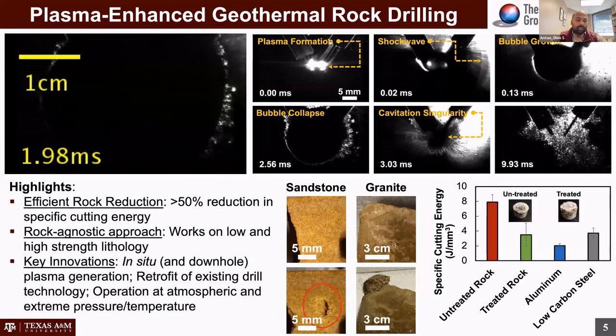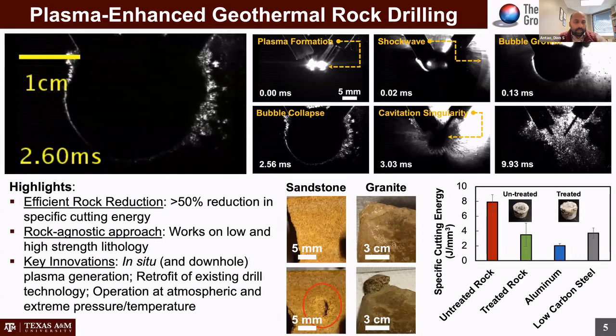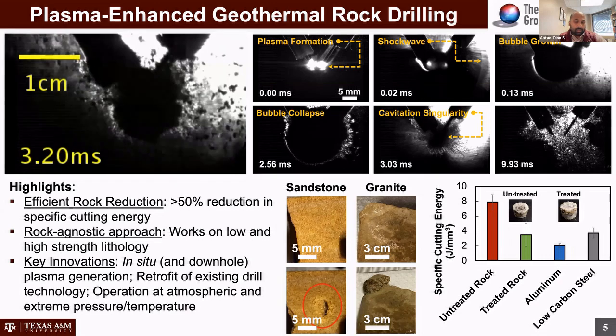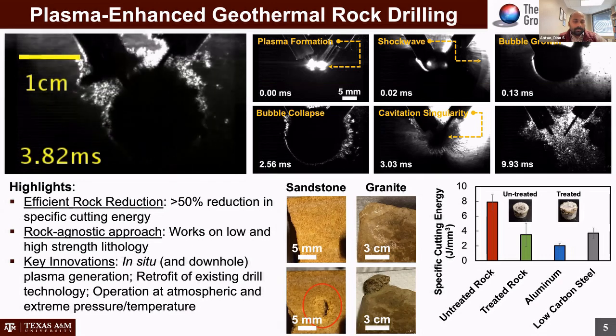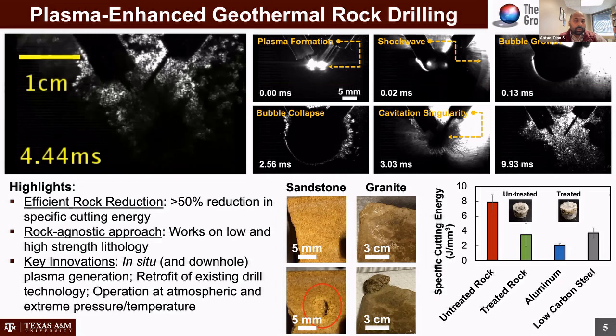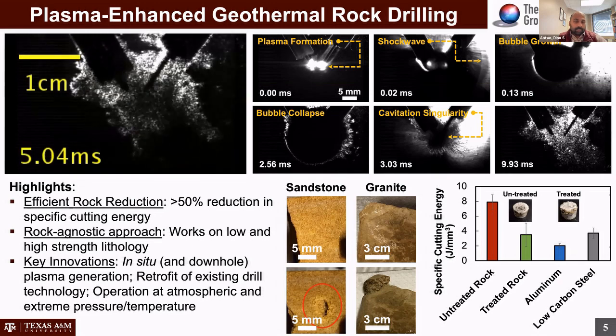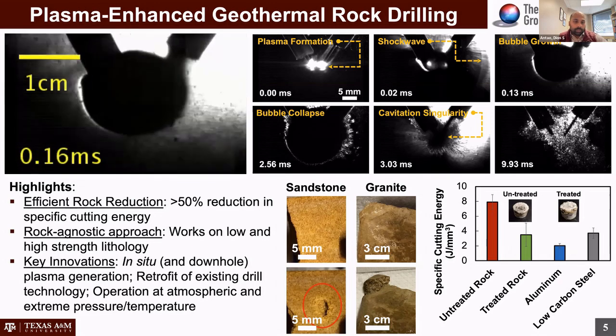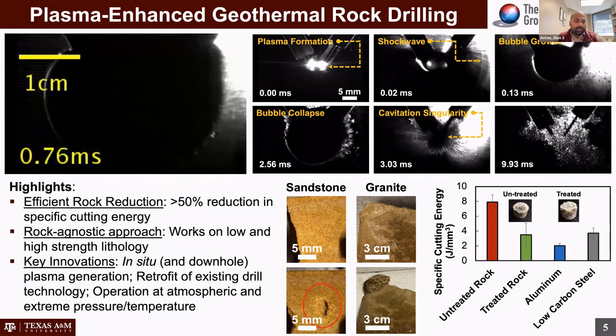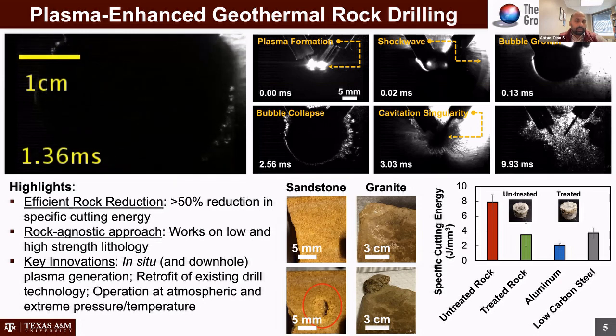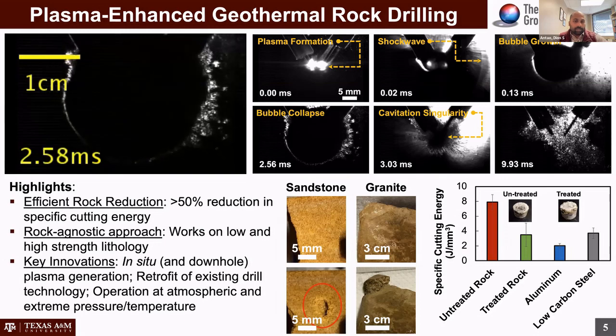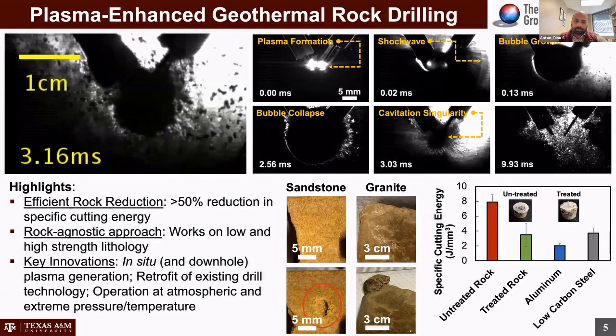And so plasma is generated in situ, and that's part of what I developed for this, or my team developed for this technology. And we can also operate these plasmas and this technology from atmospheric pressure right up to, we've done testing right up to about 5,000 to 6,000 PSI. And temperature also is not much of an issue in this particular case.